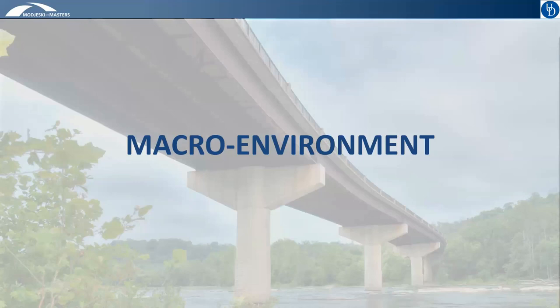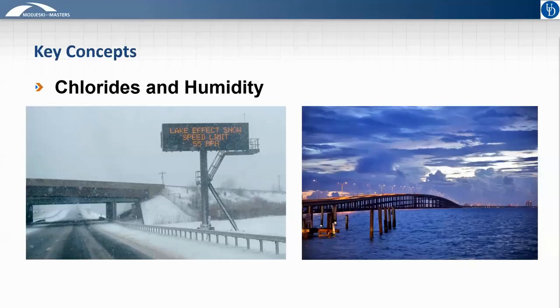So we'll start with the macro environment considerations, where our main concepts in evaluating the corrosivity of any environment are the presence of chlorides and the humidity, because both of those accelerate corrosion rates. So in short, too much humidity or too much chlorides result in poor performance of uncoated weathering steel and other structural materials. Chlorides can either be naturally occurring chlorides due to the atmospheric chloride concentrations along coastlines, or chlorides from de-icing agents. If we think about the situation shown on the left, where certainly de-icing agents would have been applied by any state transportation agency or any transportation agency,